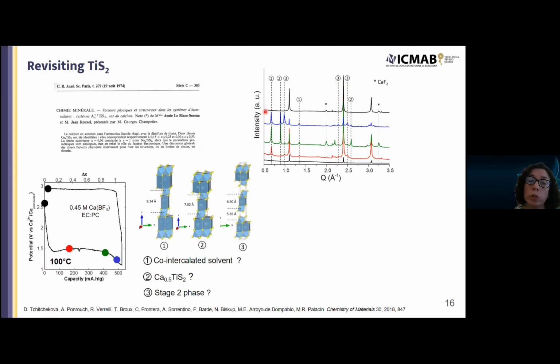And we were able to identify some of them. For the first one, the one with the highest interlayer space, we believe that this phase has a solvent co-intercalated, so it's solvated calcium that intercalates. Then phase number 2 would be the same phase with naked calcium that Jean Rouxel had prepared in liquid ammonia, and about phase 3, it could be maybe a stage 2 phase.